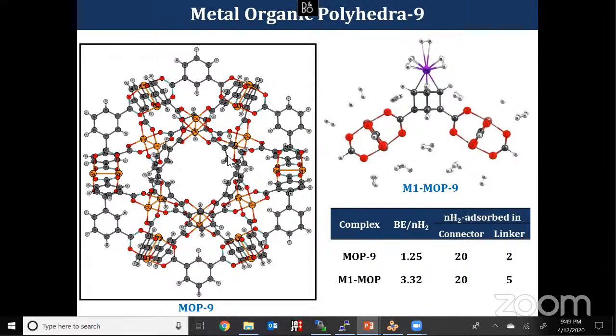So what I did is I replaced the existing benzene group with the cubane molecule and calculated the basic fundamental unit. These are the basic fundamental units available in the crystal structure. So we quantified quantum chemically the hydrogen storage capacity of the material, and we found that the presence of the cubane linker helps to increase the number of hydrogen molecules on the linker. If we are able to synthesize this kind of model, it will be highly helpful to improve the hydrogen storage property of the material.